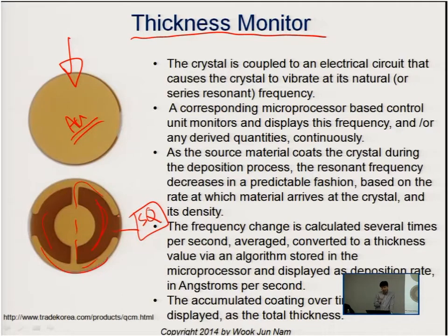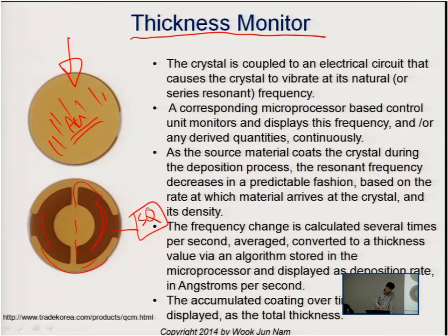So it monitors the deposition of materials on one side of this crystal. As more material is deposited on one side of the gold electrode, the resonant frequency of the quartz gets slower and slower.